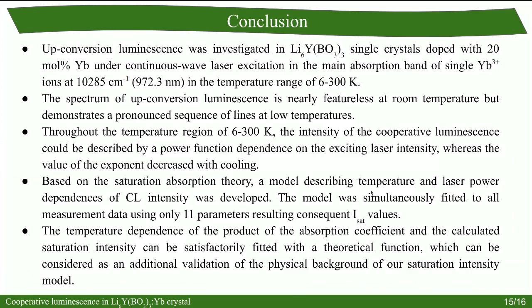So the conclusion: upconversion luminescence was investigated in a lithium-yttrium borate single crystal doped with 20 mol percent ytterbium under continuous wave laser excitation in the main absorption band of the single ytterbium ions at 972.3 nanometer in a very wide temperature range from 6 to 300 Kelvin. The upconversion luminescence was found to be featureless at room temperature, but it demonstrates a pronounced sequence of lines at low temperatures. Through the temperature region where we investigated the sample, the intensity of the cooperative luminescence could be described by a power function dependence on the exciting laser intensity, whereas the value of the exponent decreased with cooling.